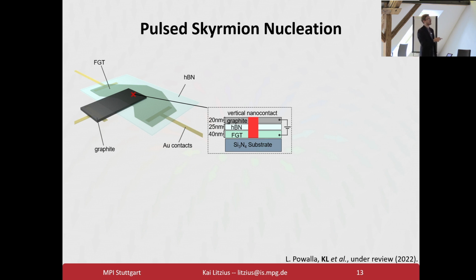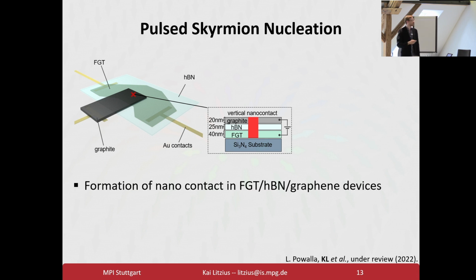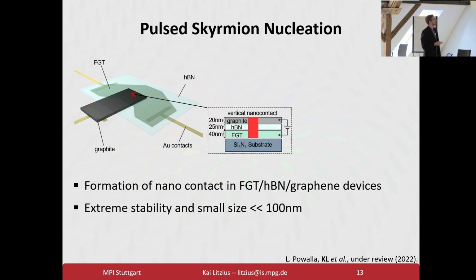And now we can shoot a nanocontact through it vertically. Essentially we generate a hole in the hBN layer, and the graphene forms a nanocontact with the FGT and allows you to pass current through it locally inside of a 2D sheet. So at one point you get a current, and everything else is untouched by this. So even in a 2D area, you can now selectively write at one point. So what does it actually look like? Oh yeah, I forgot. The contact is also very small. It's far less than 100 nanometers. We assume it's around 20 nanometers, the resolution limit of our technique.